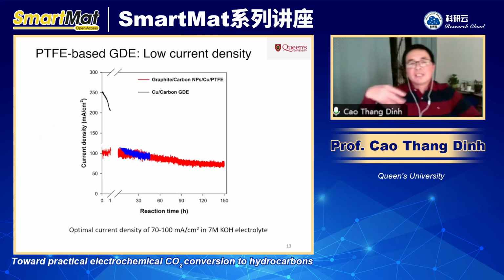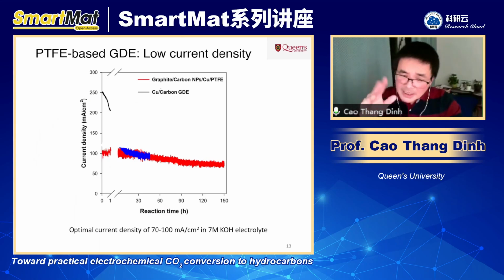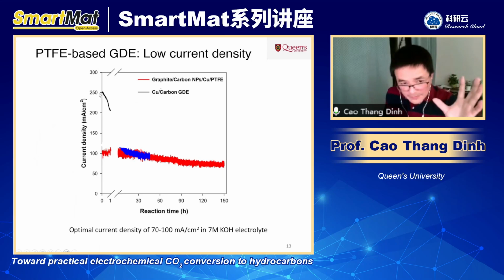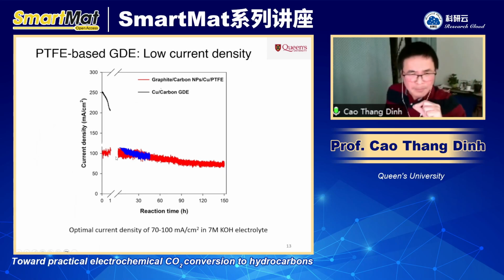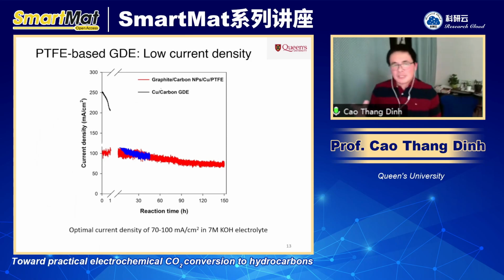But one of the challenges with the PTFE substrate is that the surface current of the PTFE is pretty low compared to the carbon substrate. So what you can see from this graph is that even though the carbon is not stable, when we run at the same potential, we observe much higher current for the carbon, right? It starts at 250 milliamp, while at the same potential the PTFE is around 100 milliamp current density. So we have a pretty low current density for the PTFE substrate. Now the question is, is there any way that we can improve the current density on the PTFE substrate?